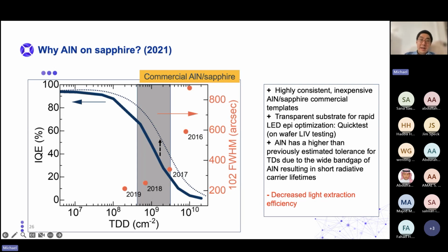A huge downside of aluminum nitride on sapphire, even today, is the decreased light extraction efficiency. The interface between aluminum nitride and sapphire is highly reflective, and a majority of the light that gets emitted towards the substrate gets reflected at that interface and does not leave the device because of total internal reflection.